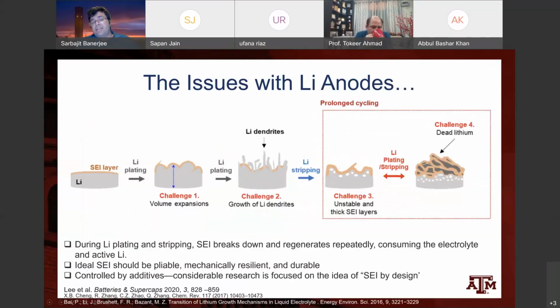Fundamentally, as the lithium is being stripped and plated, the volume of the lithium is going to change. The conformal SEI layer on the surface oftentimes will crack, and the cracks will appear in different places, and this will result in unequal lithium plating in the regions of the cracks, which will then result in dendrite formation. This is a major problem. Over prolonged cycling, you end up getting SEI layers that can be highly irregular and as much as several hundred nanometers thick. And then some of these layers will start getting pinched off, creating these regions of dead lithium, right?